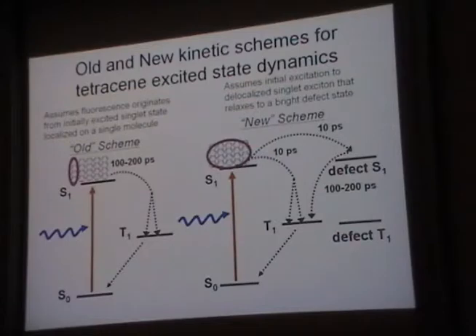Also, then you have defect states. They don't have a big effect on the transient absorption spectroscopy, but they have a big effect on the luminescence, right? Luminescence is always going to be very sensitive to defects. So in some cases, what we see, we believe, is this initial state decays very rapidly. That's our 10 picoseconds. Some of it goes to a defect state that then decays over 100 picoseconds. That's what you see in the luminescence. So this guy is a good shadow for the sort of heavy lifting singlet state, but he's not the main story. The main story is these guys. These guys recover. You get defect, you get that delayed fluorescence, and they recover, and the bleach recovers, and everything seems to be sort of self-consistent.